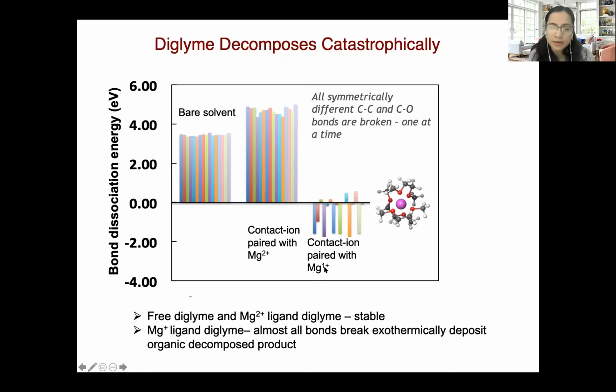So what's happening here is that at very low concentration, when it's only the solvent that's binding with the cation, during the charge transfer process, because of this partial reduction, the solvent becomes highly unstable, and that results in decomposition of the solvent and an even worse layer at the interface compared to what we were forming with the anion decomposition.